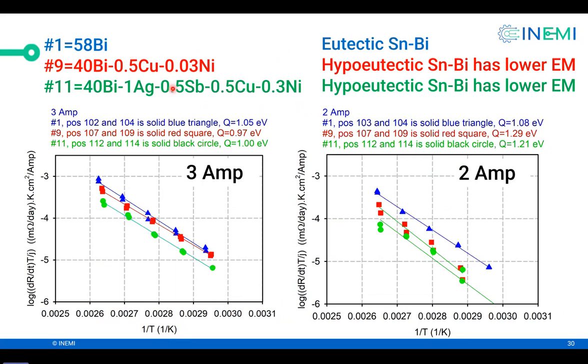And now this is the third run. Again, we have the eutectic, which is blue. 9 is the red one, which contains copper and nickel. And the green one contains silver, antimony, copper, nickel. You can see the green one, which contains silver and antimony, is less, but the one that contains copper is more. So basically, the bottom line is the hypoeutectic tin bismuth has lower electromigration, but maybe copper increases electromigration somewhat.